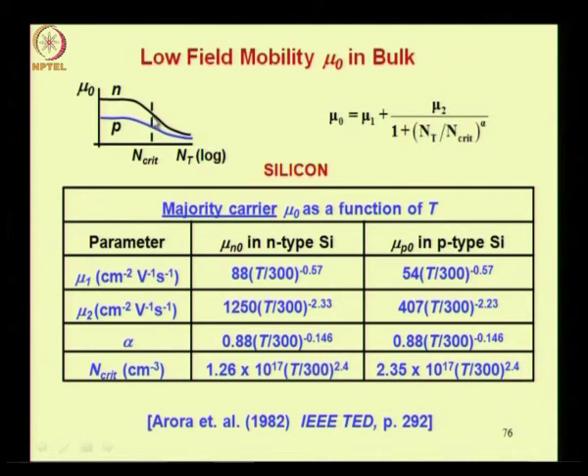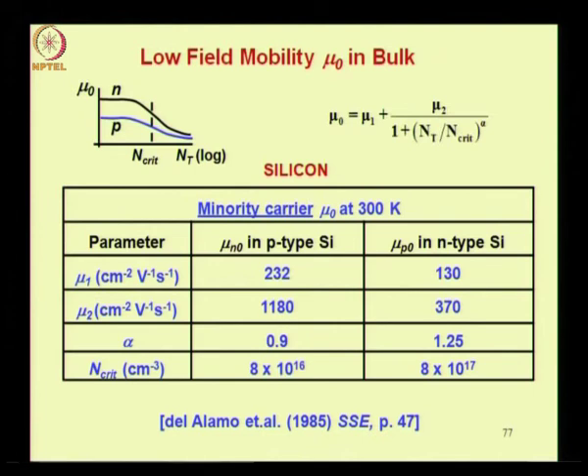Okay. So your n critical, therefore on this graph, would correspond to a point here, where mobility would be half of the maximum. This point is around 10 power 17 per centimeter cube for silicon. It is useful to note some of these values. One can give the values for minority carrier mobility. Some people have measured and given these values. Evidently this is a curve fitting exercise. So these have been given for 300 K. General results as a function of temperature are not available that readily.